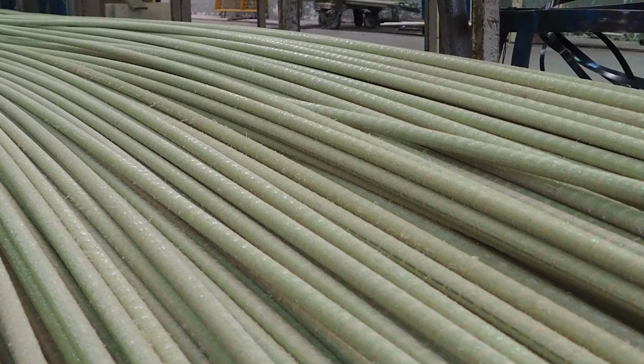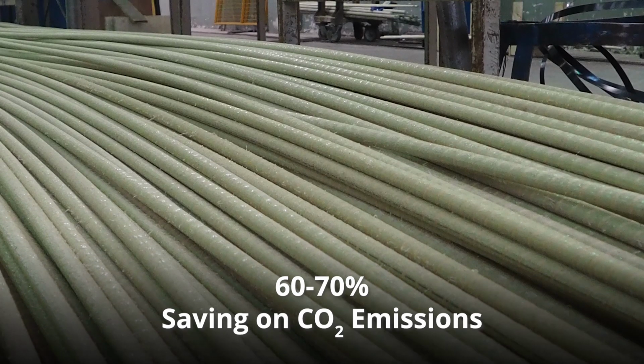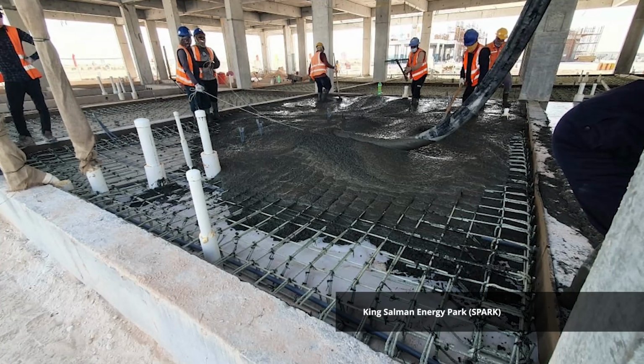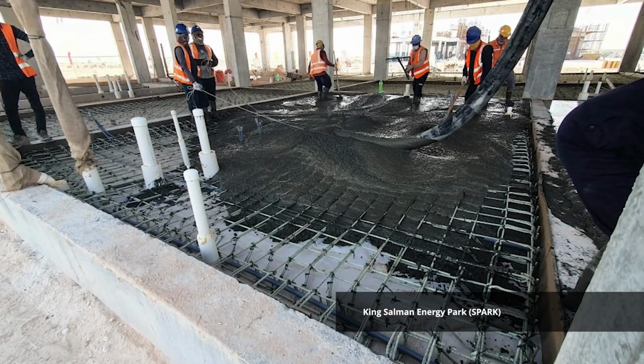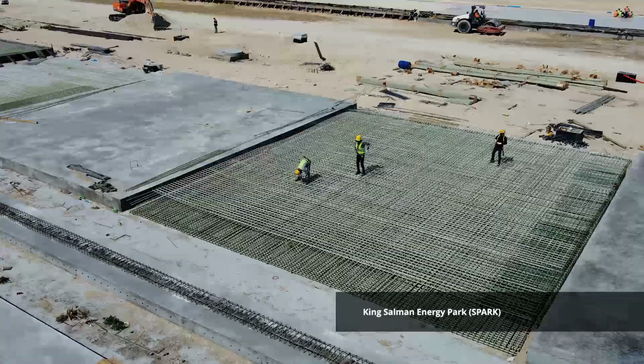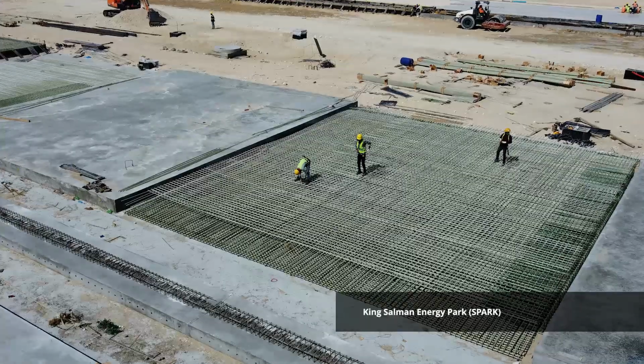Second is the GFRP rebar in itself. On average, we cut down the CO2 emission compared to traditional steel rebar by about 2/3. 60-70% reduction on most projects on the rebars. And for the reason I mentioned also earlier with the concrete cover, and some other aspects, there are projects where we managed to reduce the quantity of concrete consumed as well. In those projects, we generally managed to reduce the embodied carbon, the CO2 emission, by 50% for the whole concrete structure, not just the rebar, but the rebar and the concrete. We have projects where we reach 50% reduction, which is massive.